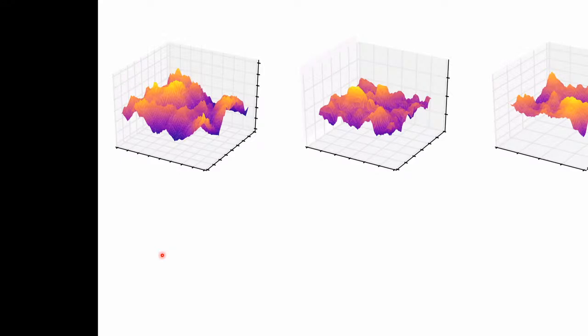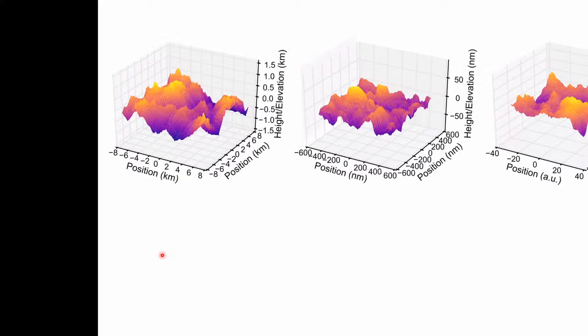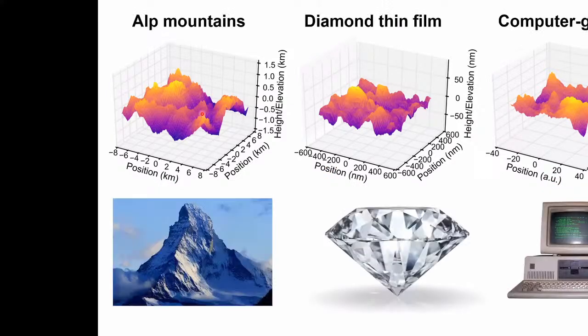These look very similar, but they also don't have a scale bar. If I show you the scale of these measurements, then it immediately becomes clear that this is something completely different. The left one you see is in kilometers. This one is nanometers, and this is AU, arbitrary units. The left plot is actually a section of the Alp mountain range. This is an AFM scan of an ultra nanocrystalline diamond surface from Tevis Jacobs' group in Pittsburgh, and this is a computer generated surface that I generated in the computer.